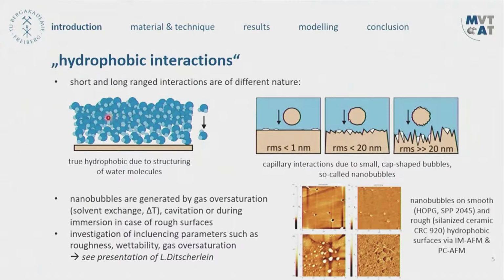We see here there are, let me say, fewer atoms or molecules than above here. We get a short-range structuring of the water at the hydrophobic surface, generating an attractive force, because everything which has another surface energy than the surface tension of the water is attracted to that surface. But this does not reach very long distances, perhaps some nanometers, but that's all.